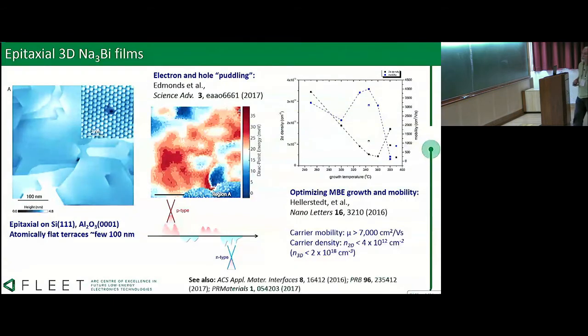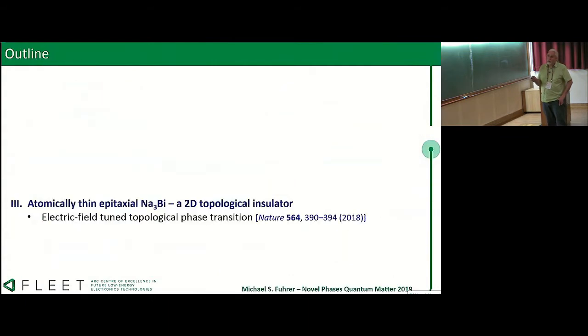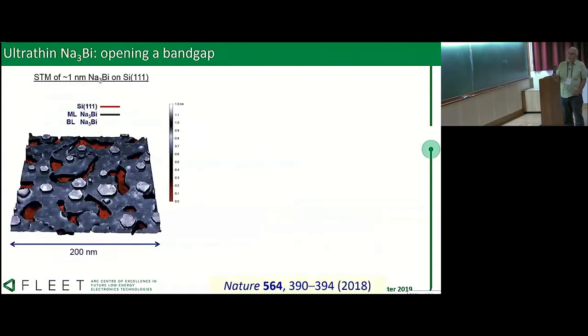Okay, and there's other work that we've done that I won't talk about. So really, I want to get to what happens when you go to 2D. I think that's maybe more interesting. So we can thin this material down. This is a film deposited on silicon, so it's nominally 1 layer thick. And what we see is regions of bare silicon in red. This is, again, scanning tunneling microscopy. We see monolayer regions in purple, and we see the start of bilayer regions in this light gray purple color. So we can grow a film that's mostly monolayer. It has some bilayer regions.